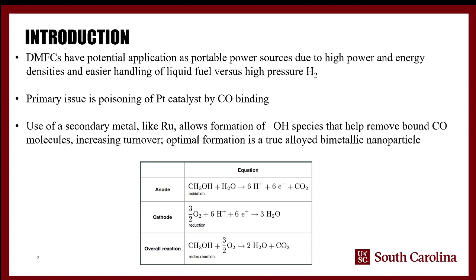The primary issue, however, is platinum catalysts are the gold standard, but platinum and carbon monoxide bond very strongly. Because of that, when you do methanol oxidation, one of the main reaction steps involves the formation of CO. That CO will bind to the platinum catalyst site, and once that happens, it doesn't really come off easily. As the reaction proceeds, the catalyst sites fill up, and so what you see is a drop off in the power density of the cell itself, because your active catalyst sites are being occupied for a long time by these CO molecules.